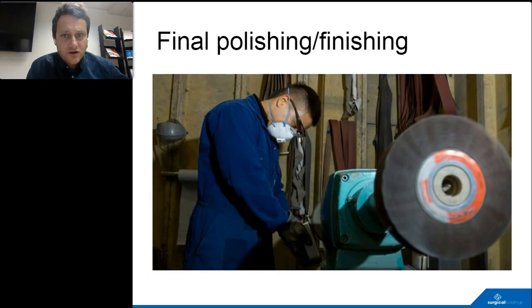So final polishing and finishing is something that's often overlooked, for me. Unfortunately, the graphic is overlapping some of my text there, but essentially the easy way to explain this is the smoother the surface, the better the corrosion resistance. We look to achieve under 0.2 microns in terms of how smooth the surface is. The rougher the surface, the higher the wettability of the steel. So if you drop some water onto a rough surface, it won't flash off.